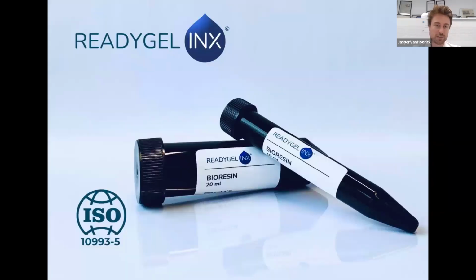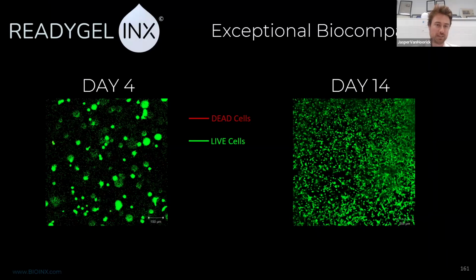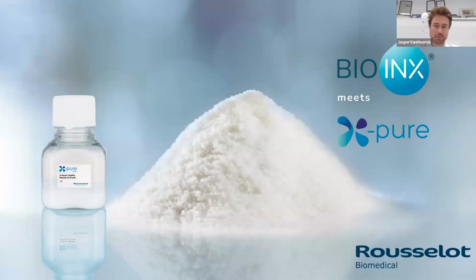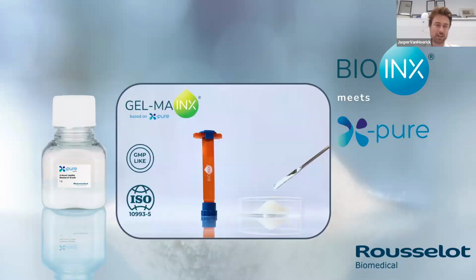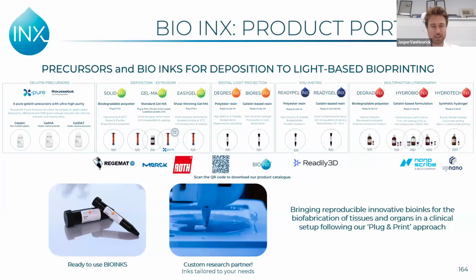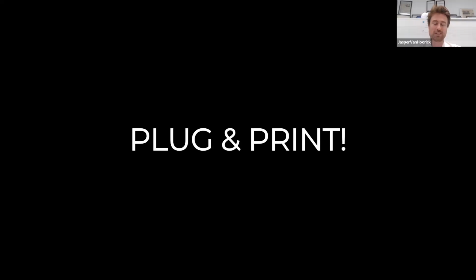The benefit of it being so fast and using blue light is it has exceptional biocompatibility. So there's almost no dead cells after printing. And since it's so fast, this opens up the dream that one day you could have a bioprinter inside the operating theater where you could harvest your cells, 3D print your structure and put it back in. But for that, of course, you need biocompatible materials, for which we are collaborating with Rousselot, the biggest gelatin supplier in the world, with whom we launched last year the very first GMP-like material. So if you want to go into the bioprinting field yourself, we have compatible materials for all printing technologies, which are plug and print, which is important to translate this technology from the research into the clinics.